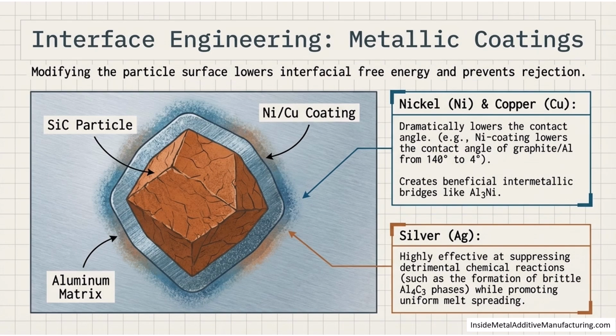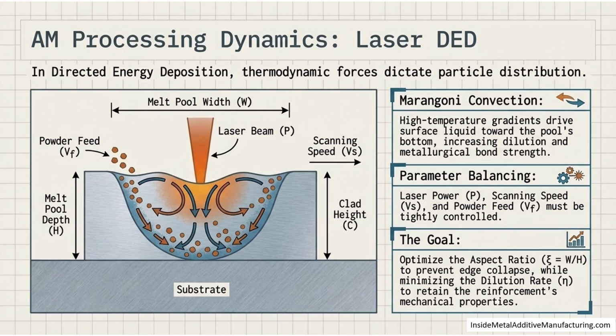By applying metallic coatings like nickel or copper to our reinforcement particles, we dramatically lower the contact angle. For example, a nickel coating can drop the graphite on aluminium contact angle from 140 degrees to just 4 degrees. This facilitates the creation of beneficial intermetallic bridges, while silver coatings can suppress the formation of brittle, detrimental phases like aluminum carbide. Now let's look at the build dynamics in directed energy deposition.